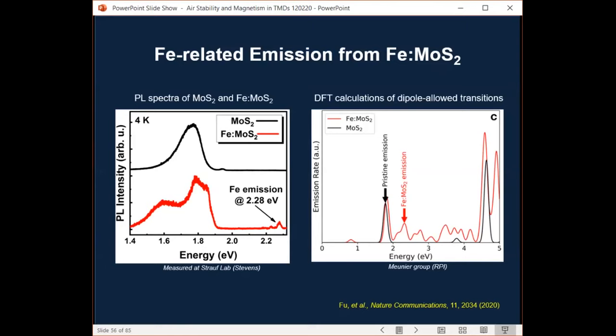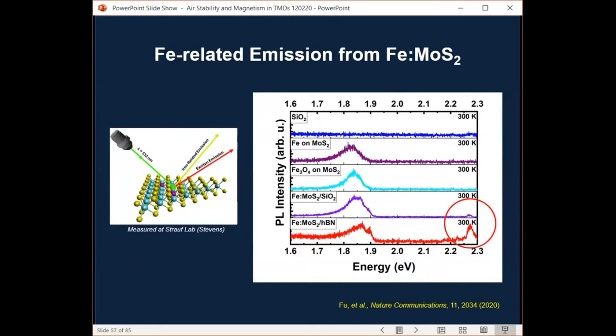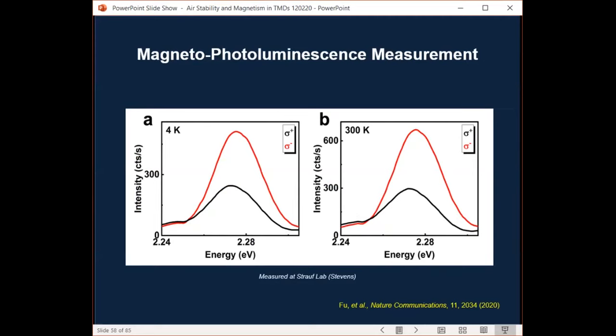And here confirming the substitutional doping is critical since the magnetic transition must come from the doping of iron atoms, not from other sources such as residues on the surface and interstitially doped atoms and so on and so forth. So we perform this higher angle annular dark field STEM imaging and on the left is for the iron doped tungsten disulfide monolayers on the right is molybdenum disulfide. Here the brightness of atoms in STEM images is directly proportional to the square of the atomic number. So we can confirm the substitutional doping of iron atoms replacing tungsten or molybdenum sites using the STEM intensity profile on the center here. Now, one of the key features in our findings is the iron related emission from iron-doped molybdenum disulfide. The figure on the left shows the low temperature PL emission of the molybdenum disulfide and the iron doped molybdenum disulfide monolayers, where we find the emission peak here at 2.28 eV, which is very distinct from the sample.